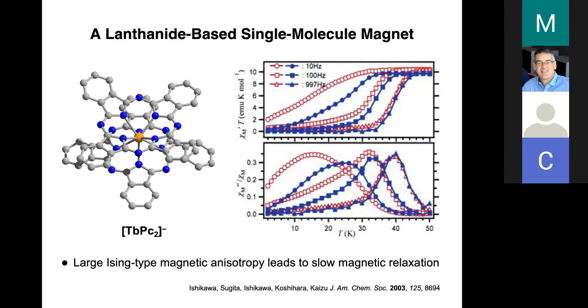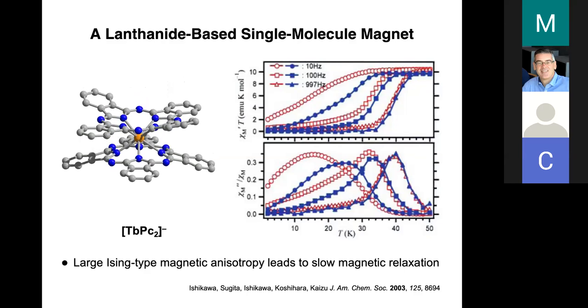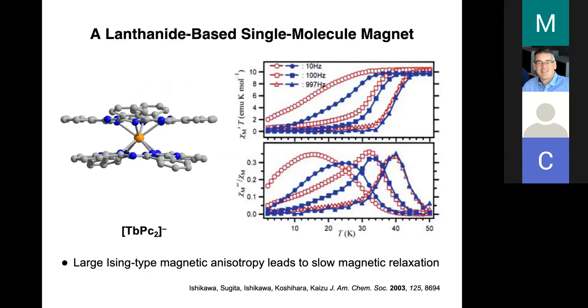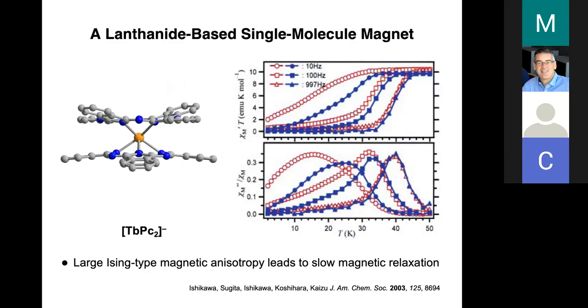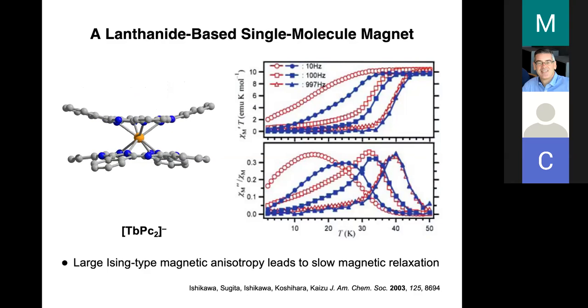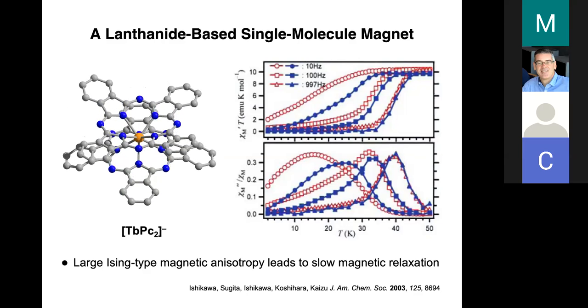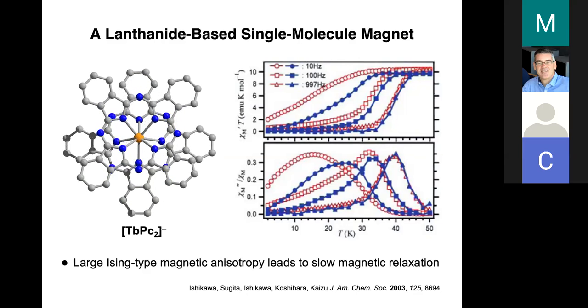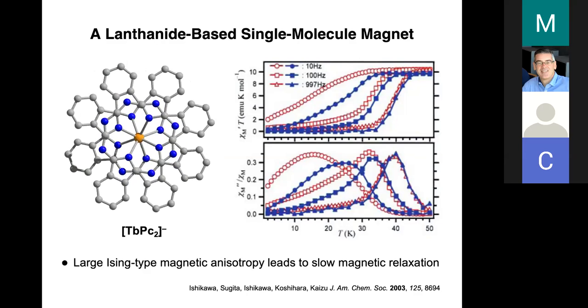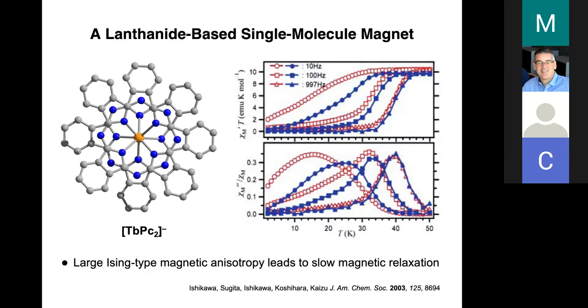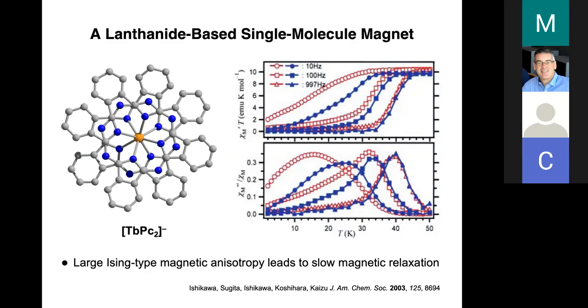And this is the idea that you're probing the magnetism with a magnetic field that's switching directions at a very specific frequency. And as you vary the frequency and match the relaxation time for the moment in the molecule, you'll see a missing component from the measured susceptibility.